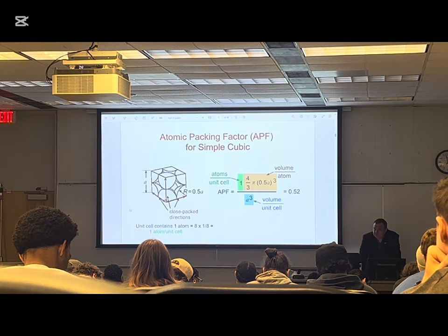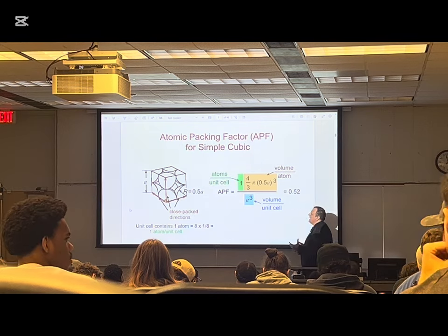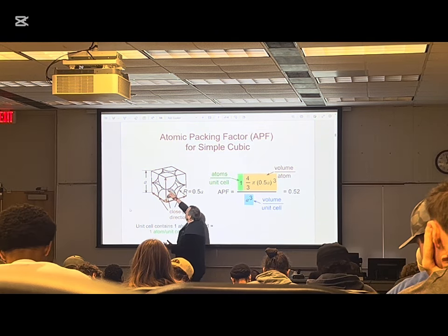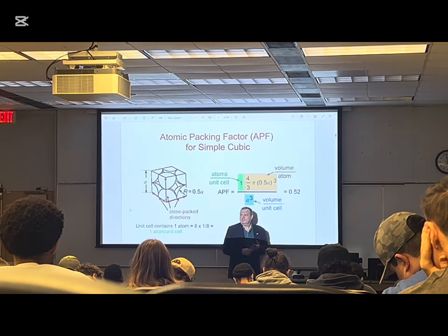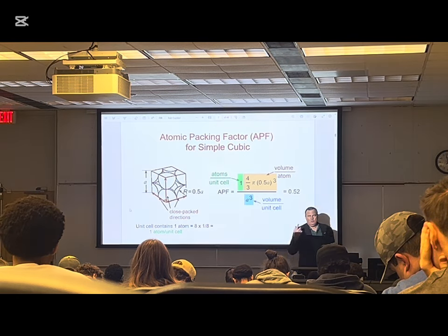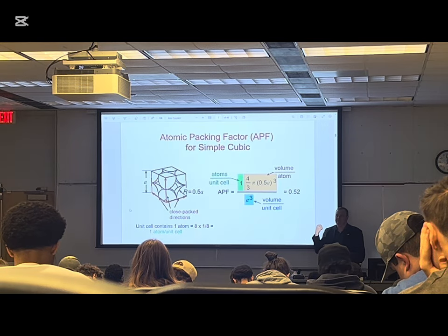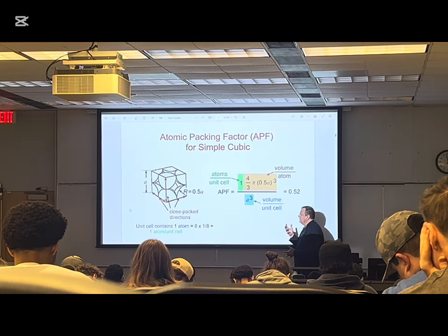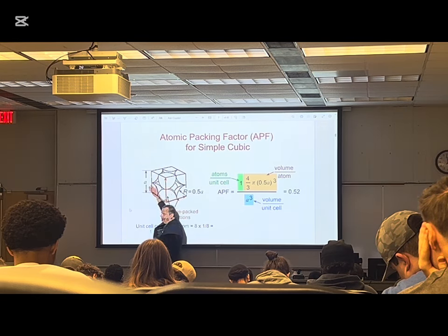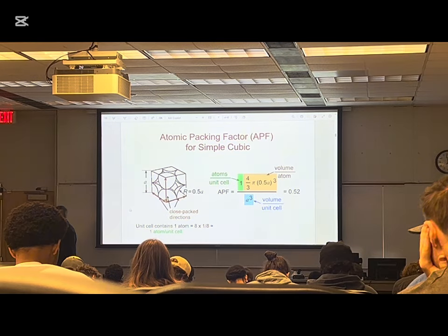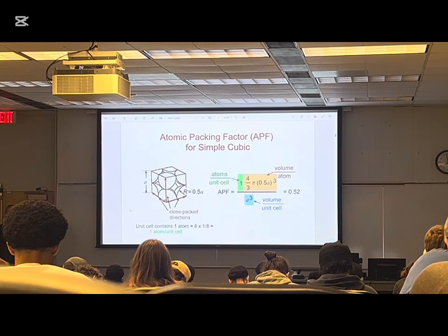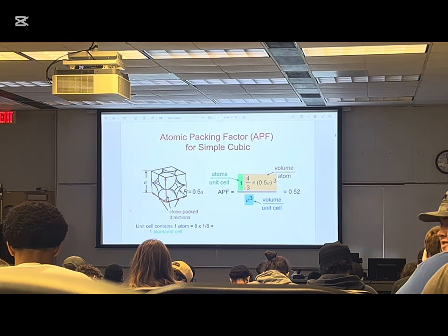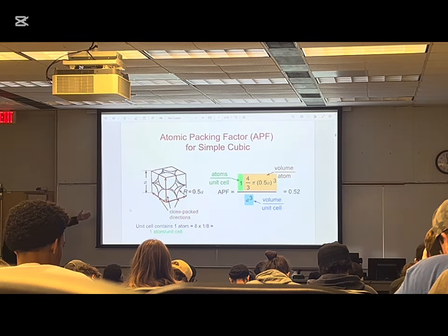Now, how many fractions of an atom do we have here? We have 4 on the top and 4 on the bottom, so overall how many? 8. And what fraction of a sphere is this? Like, if you were to put them all together, what are you going to have? You're going to have one sphere. So we have 8 fractions of 1/8 of the full atom, and there are 8 of them. How many full atoms do you actually see here?